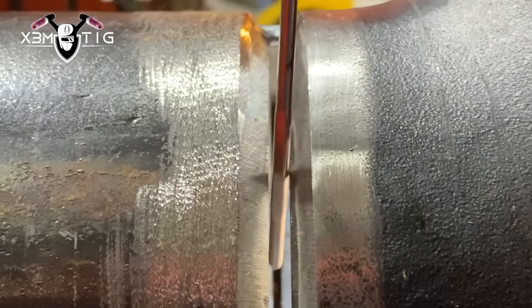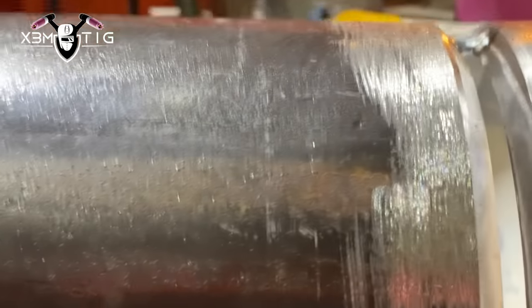For the gap, gap size 5/32. This is what I usually like to use on my joints when I'm doing 6G. For you it might work a little bit different. You can wiggle 1/8 all the way around. As I can make it 1/8 rod all the way around, this is a good joint for me, good prep especially at the bottom.